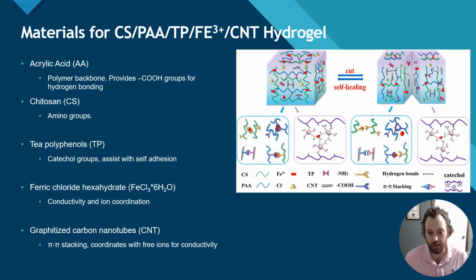Above me, you'll see a figure that illustrates all of the different intramolecular forces that we have going on in our compound. Starting here to the left, we have an example of amino groups coordinating with the ferric ions. We have pi-pi stacking between a combination of two carbon nanotubes. We have coordination amongst the carboxylic group and amino groups, and we have coordination amongst just the carboxylic groups themselves. Adjacent to that, we also have the catechol groups. This large and wide breadth of intramolecular forces will come in handy when it comes to things like self-healing, where these interactions can bring two pieces of the polymer back together due to their strength.